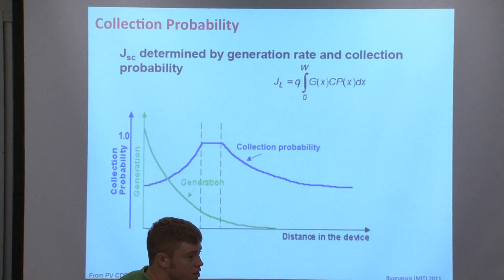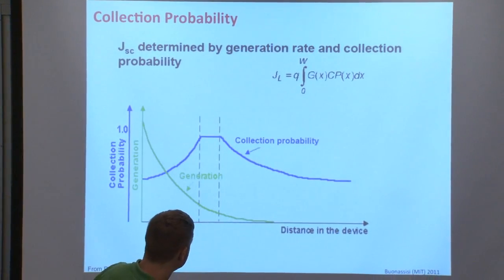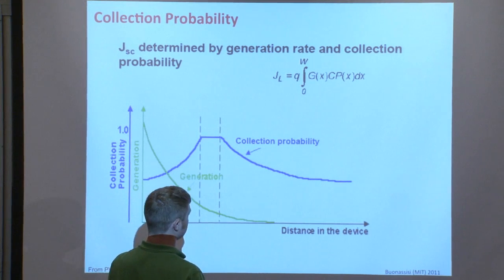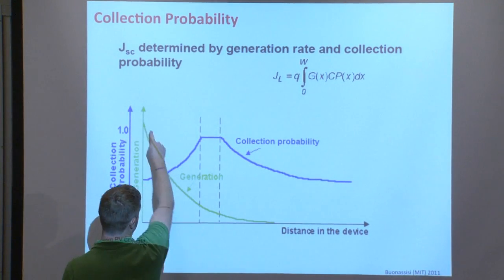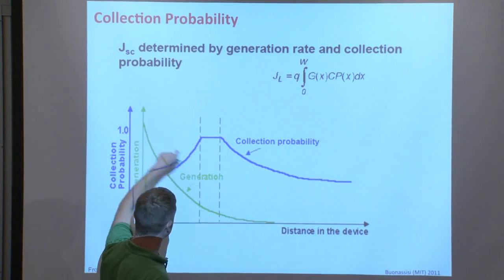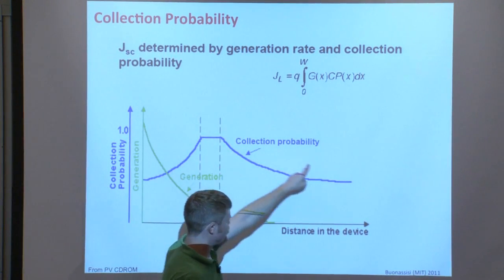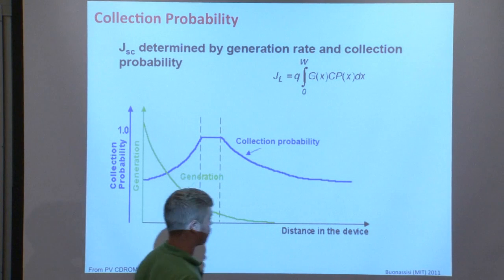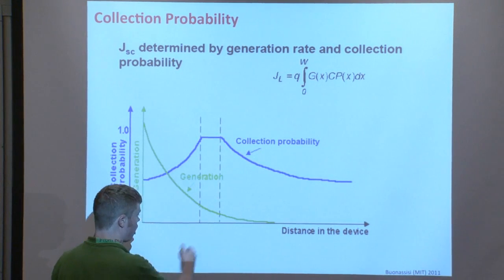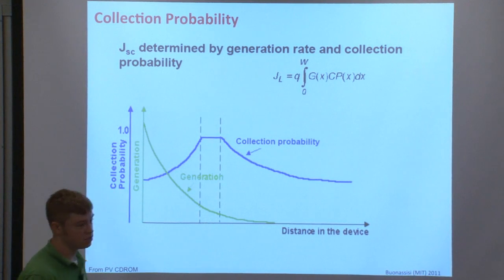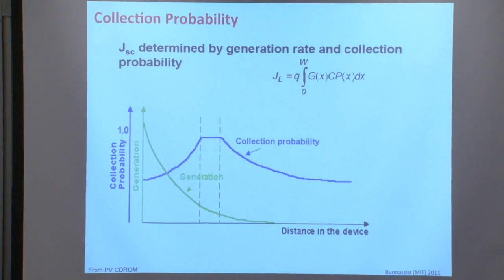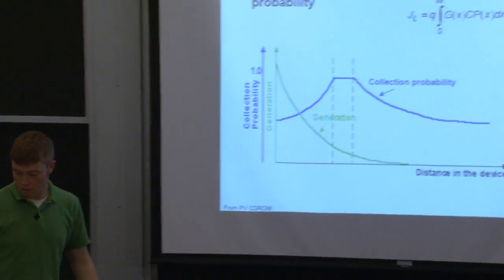Sorry, say that again? People just approximate it as your first region there and don't care about the junction and afterwards. For certain wavelengths of light, let's say this curve, this is kind of representing Beer-Lambert's law. If it attenuates less drastically, if that characteristic absorption length is a lot longer than this length here, then yes, you can assume that this emitter region is negligibly thin. That's a little bit of what the homework goes over as well in problem 3. Excellent question.